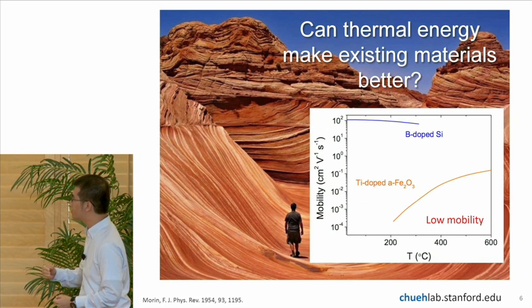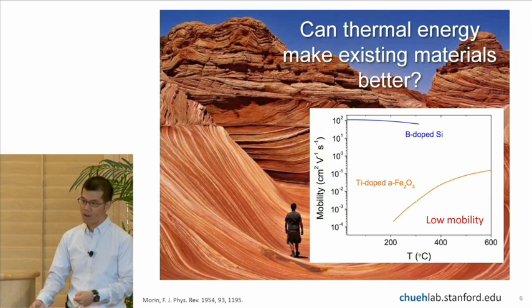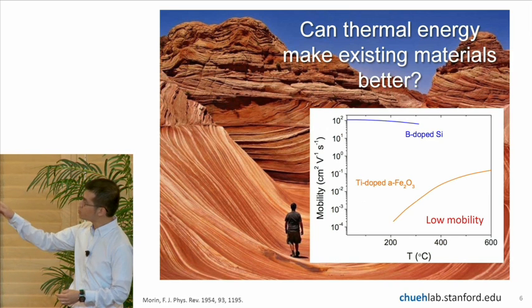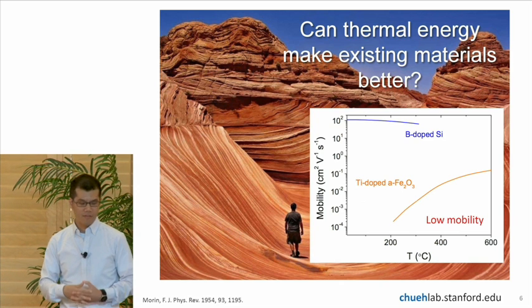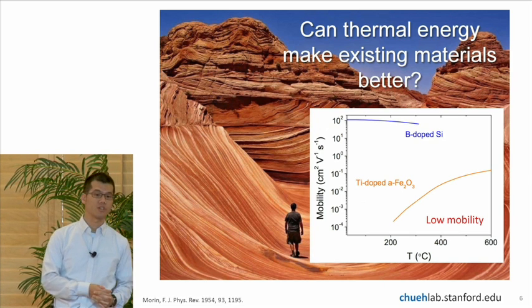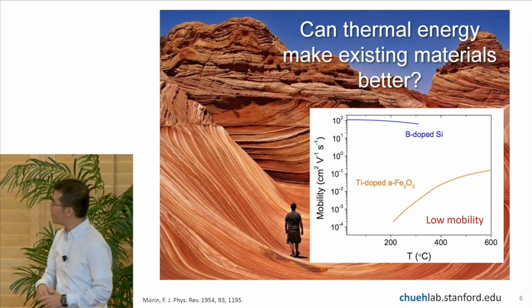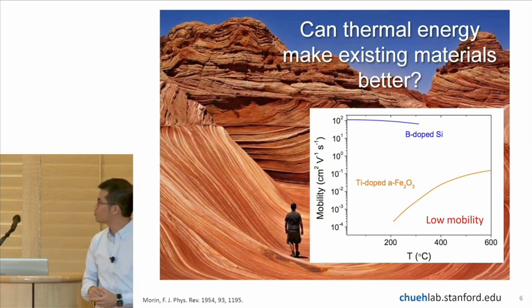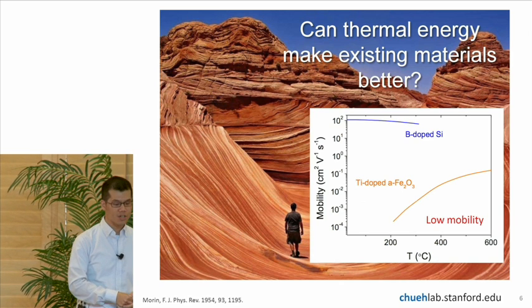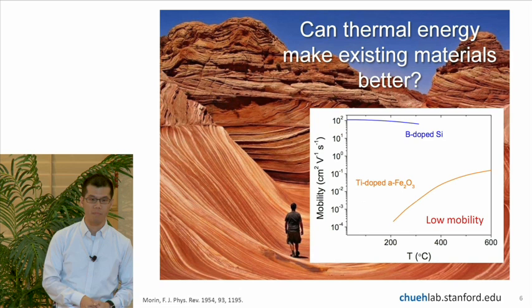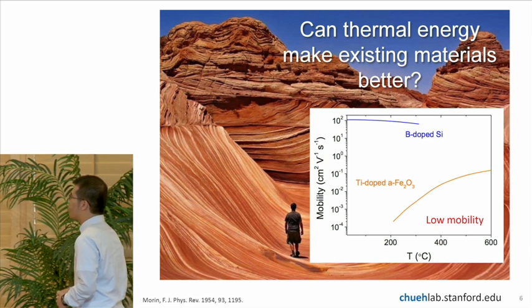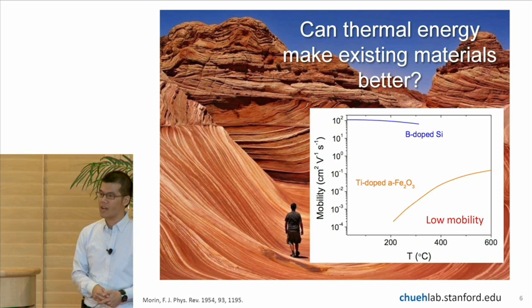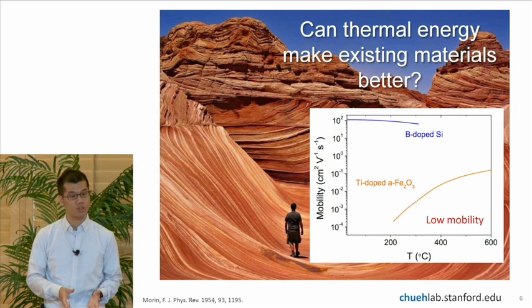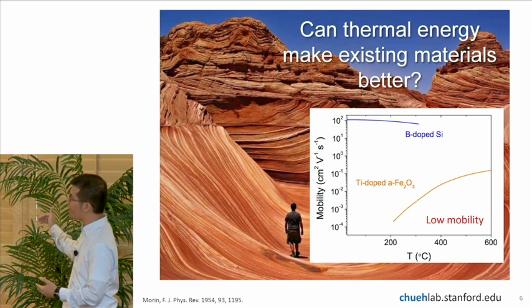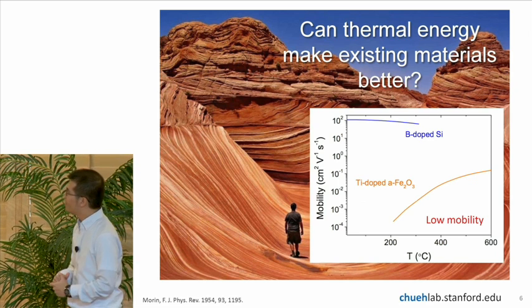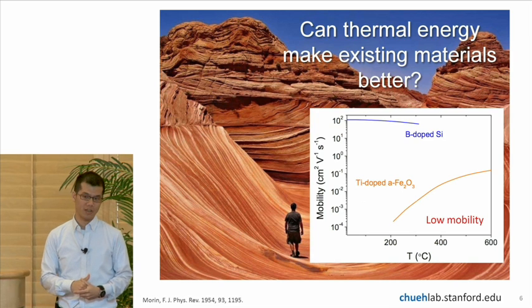So the electron barely moves, and this is due to strong interactions of the electrons and the ions in the crystal lattice. So here I show you a plot of the mobility of silicon and the iron oxide as a function of temperature. And you can see silicon's way up there. It's about 10 to the 2 centimeters squared per volt per second. And iron oxide actually has mobility that is immeasurable at room temperature because it's so lousy. But what you can see, a very significant contrast between the two materials, is the slope on temperature. So while silicon decreases slightly in mobility when you increase the temperature, iron oxide actually increases dramatically, exponentially with temperature.